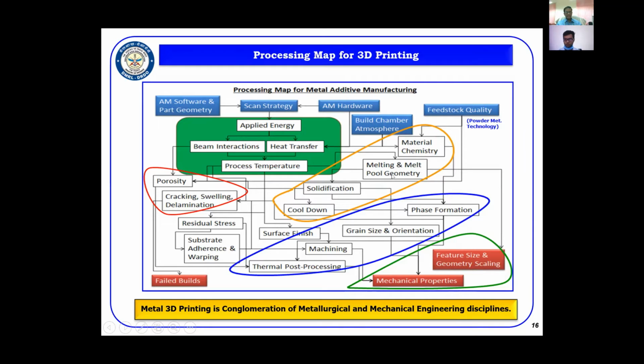And in the processing stage, the laser-metal interaction will have a very dominant effect on the process of solidification, cooling of molten alloy, material chemistry, and melt pool geometry. These processes will be directly responsible for the formation of different phases, grain size, orientation, etc., which will dictate the final properties obtained on the component, or they may cause defects on the component. So even in post-processing, thermal processing like heat treatment and hipping are all very important.